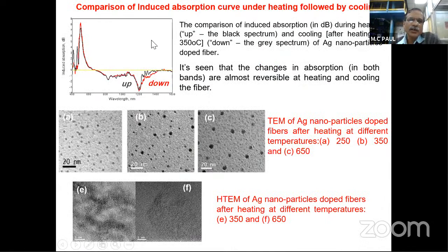This is also after heating, and then we cool. The same spectra occur, no change, so this can be a reversible process. This is the TEM analysis at 250, 350, and then 650, and gradually the size of the nanoparticle increases. At 350 and 650 we have taken high resolution images, and a crystalline plane structure appears. This is a metallic nanoparticle developed under heating at 350 to 650 degrees centigrade.